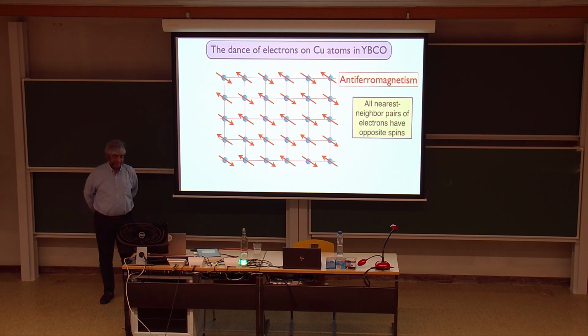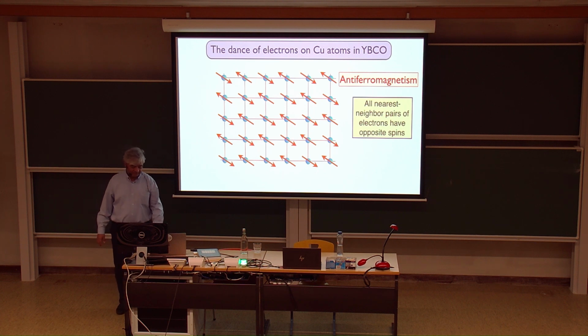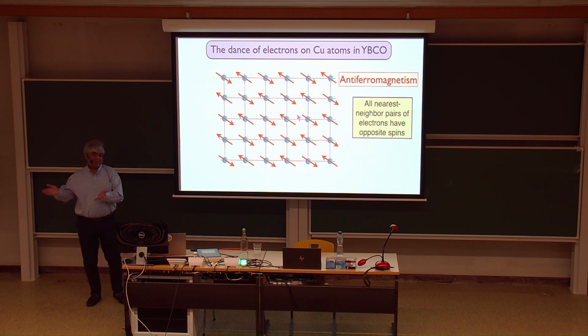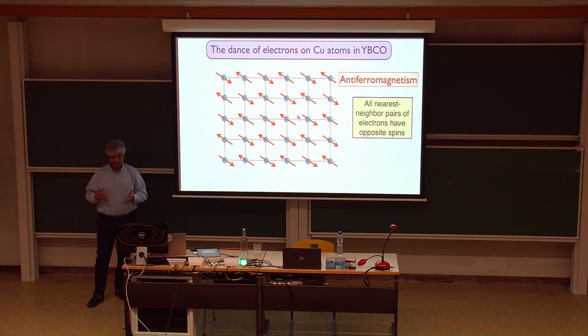So, as I mentioned earlier, when you're at p equals 0 with one electron per site, the system forms an antiferromagnet. And this is due to the exchange interaction between the spins, which is antiferromagnetic in the Hubbard model. And so you get this checkerboard structure, which is well understood and studied in experiments. However, this long-range spin order disappears fairly quickly, and it's certainly not present in the pseudogap, at least in the hole-doped cuprates. There's not even any appreciable spin correlation length. So we don't want to start from this state.